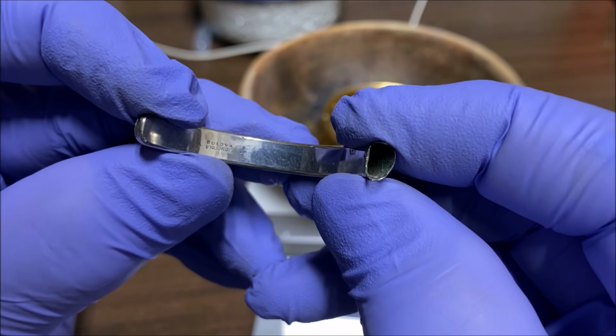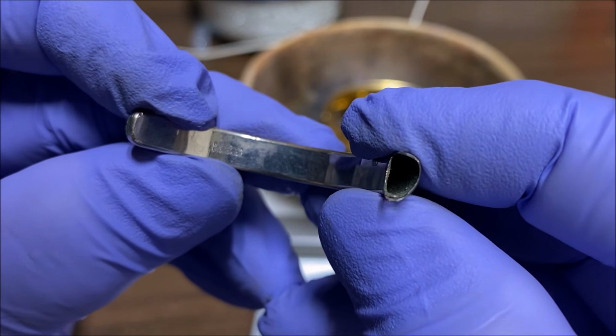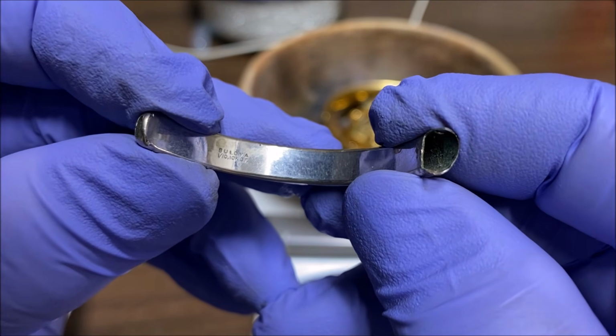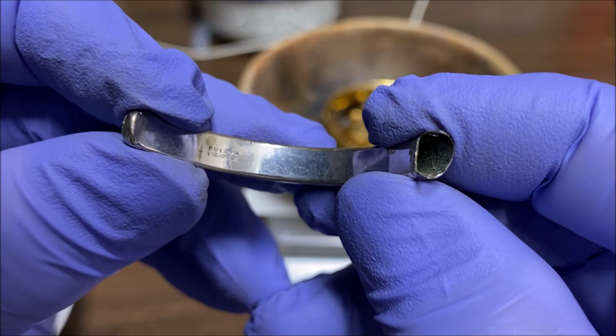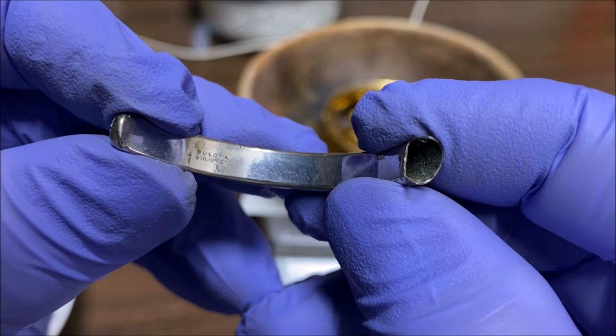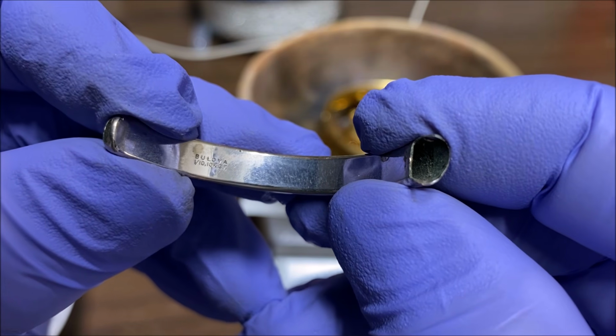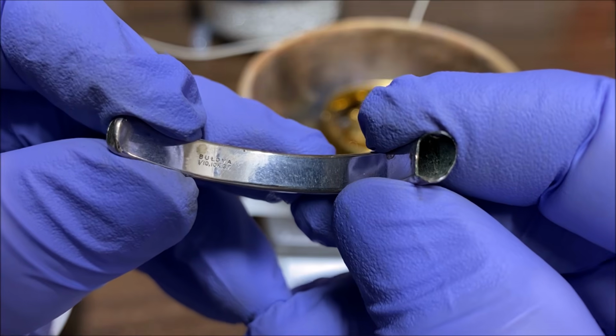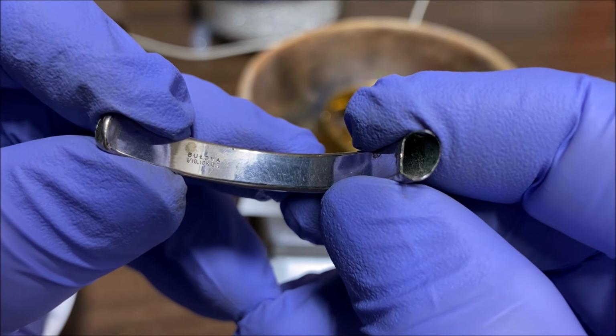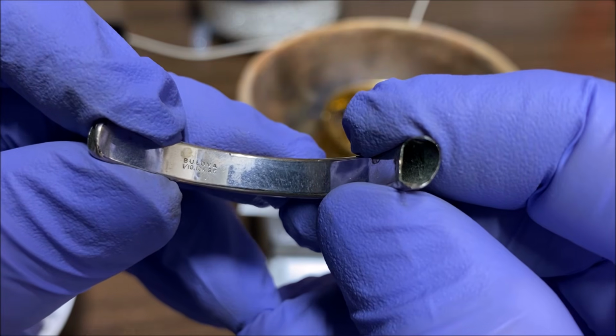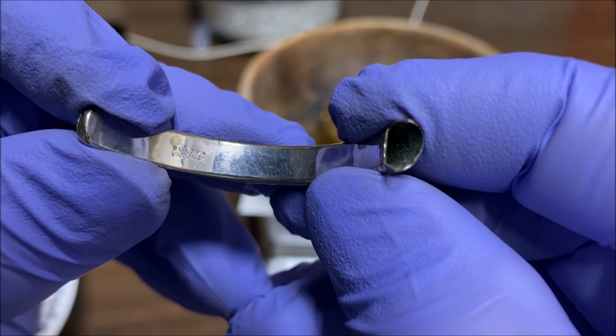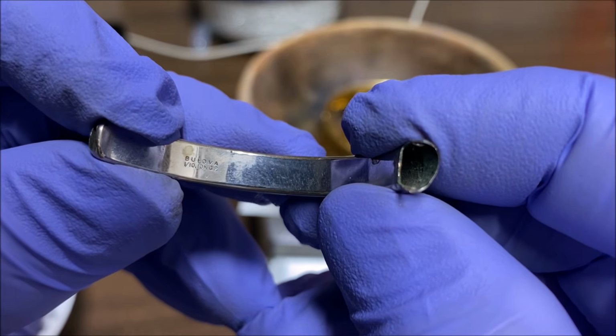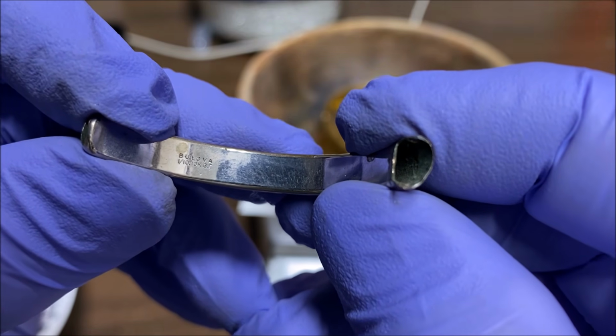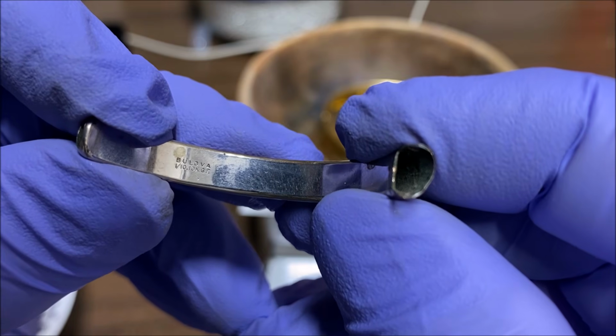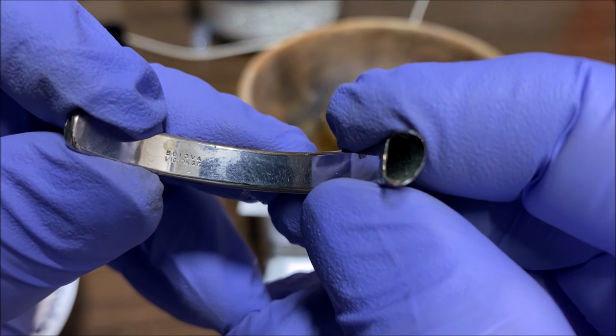All right, one more piece just to show you what we're looking at. This was a watch band, 1/10, 10K, GF. Well, once again, gold fill material is a thick coating of karat gold over a base metal, usually brass. This will test positive. If you rub this on a touchstone and put some acid on it, it will test positive for karat gold. That's because it is karat gold, a thick coating of karat gold over brass.